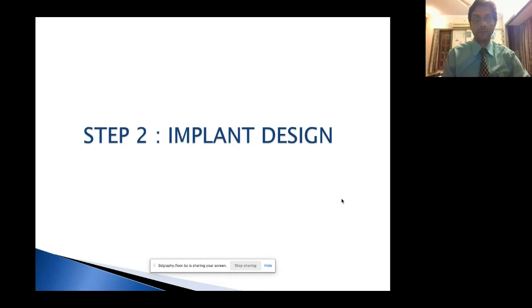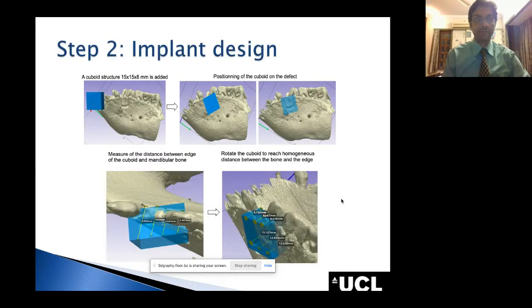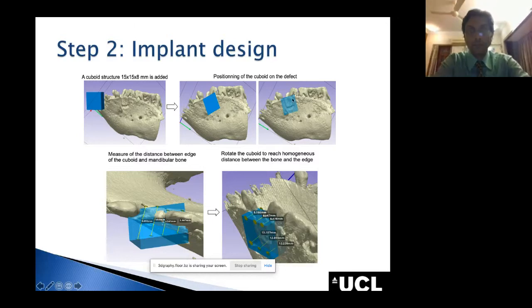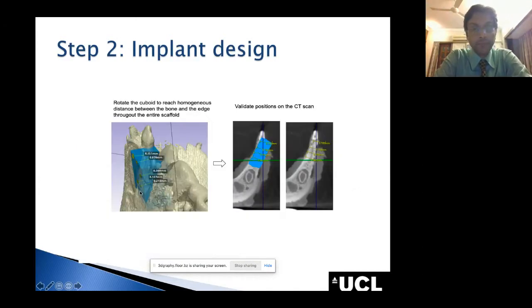The second step was to design the implant itself. So the clinical requirements for this, as Federico was explaining, were that there needs to be an 8 millimeter thickness across the jaw in order for the screw to be successfully placed afterwards. So we took a cuboid structure as a reference shape, and we placed it in front of the graft. We rotated and positioned it correctly, and we made sure that we had 8 millimeter across the whole graft. We double checked both on the visualization mask and on the CBCT, as you can see here.